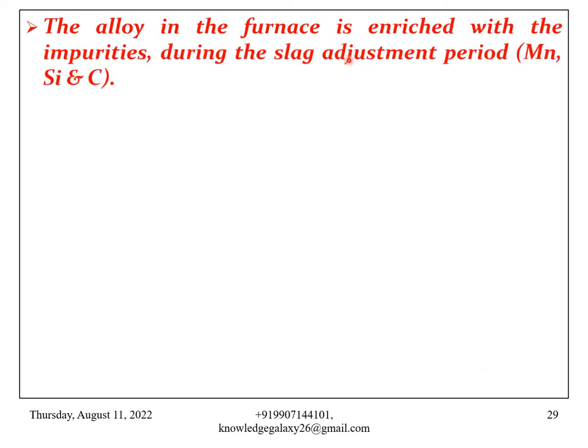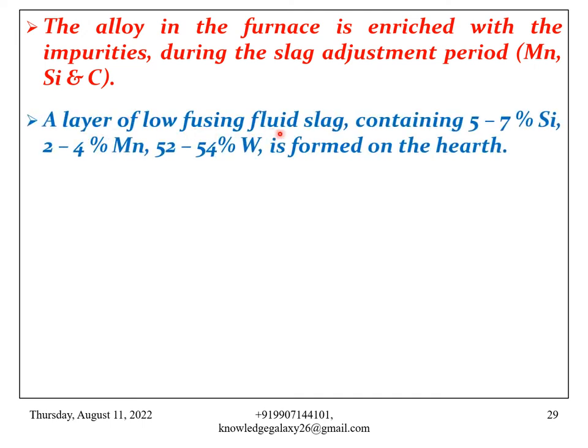The alloy in the furnace is enriched with impurities during the slag adjustment period. The main impurities are manganese, silicon and carbon. A layer of low fusing fluid slag containing 5 to 7% silicon, 2 to 4% manganese, and 52 to 54% tungsten is formed on the hearth.